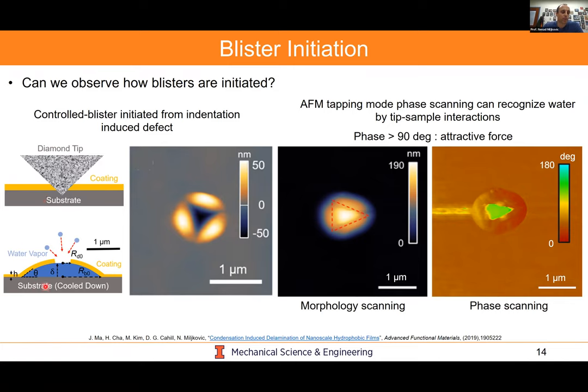Then we could actually watch how this blister grows and know these parameters through the in situ AFM imaging that we do. And indeed, what you're seeing here are phase scans in what's called an environmental AFM, where you could actually condense water while you're doing the AFM analysis. And what you're seeing here is the defect. This is the polymer film on the outsides. This is the defect itself in this little triangle. If you condense water, you'll see that water will actually form and fill the blister. And again, this phase scanning tells you that this green is water and the rest is a very non-polar, non-interacting substrate or substance. So again, further verification of our hypothesis that this is how this delamination is actually occurring.